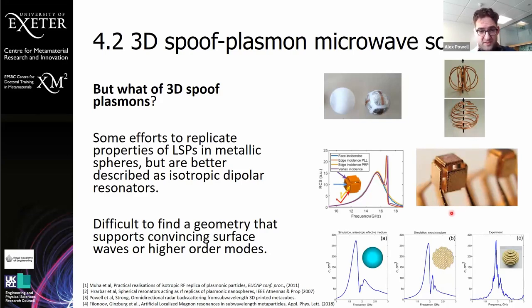One of the more interesting approaches was done by Pavel Ginzburg's group. And they actually made an artificial magnon structure, which is, instead of having a negative permittivity, they had a negative permeability, which they made by making a bunch of split rings on circuit boards and stacking them in a spherical structure. And they're able to get a magnetic resonance that they could measure from this. And that was really cool. But again, it's mostly a fundamental mode, and it will only work for a very set range of incident angles and polarizations.